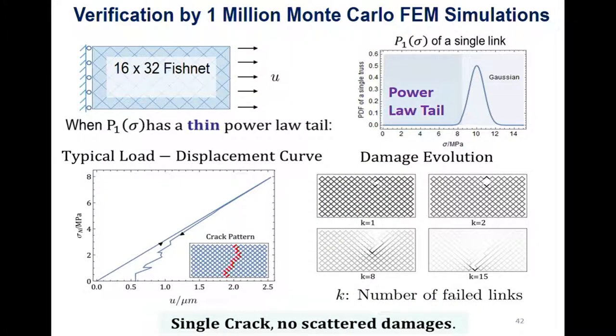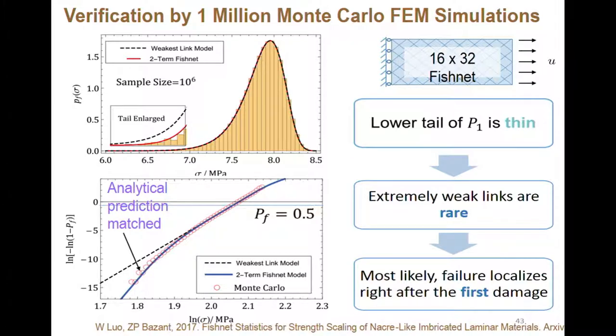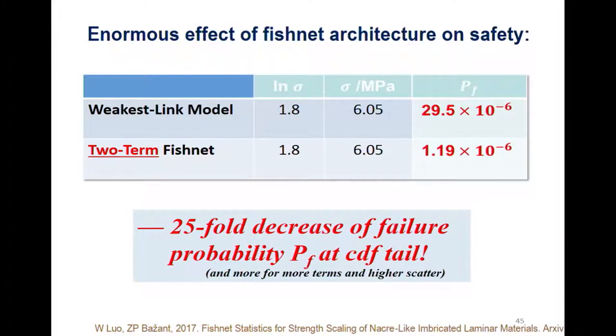All right, so here I show the distribution, the power law tail, the typical load displacement curve. This is a spread of damage from the simulations. This is the same thing in CDF, probability density function, the tail consideration. Again, analytical prediction compared. But let me point out now the gain in terms of probability. So before I show the gain of strength, probability being fixed at power minus 6.